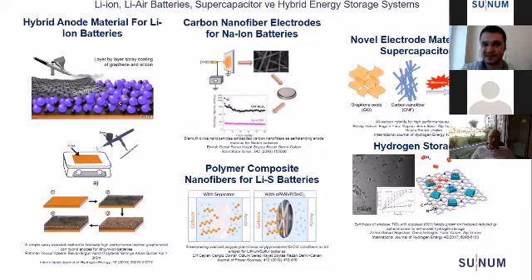On the other side, reduced graphene oxides were combined with carbon nanofiber with the microwave method and then used as electrode material in supercapacitors. In the last example, the surface of the graphene is coated with anatase, which is a type of titanium oxide. And then the hydrogen storage capability of the system was increased with that additive.